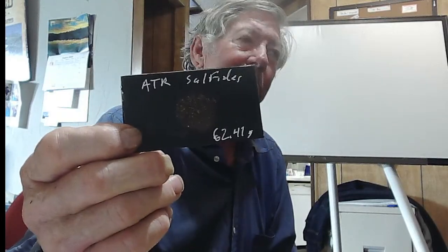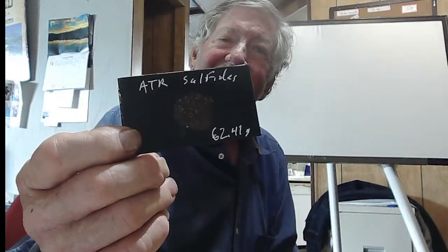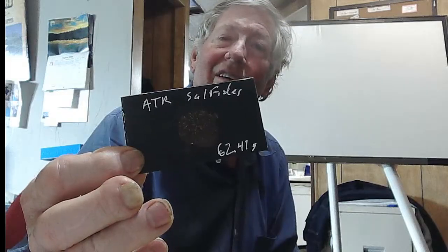I don't have a good way of taking photo micrographs right now, but I don't even need that. In some ways, I would presume this is a little better than a photo micrograph, because you can always go back to it. Once I roast this, I'll be roasting this tomorrow, then you do a similar card with the roasted concentrate and how much that weighed also. I seem to be getting, at this point, about a 25% reduction in mass, which, if I'm doing the chemistry right and the molar math, I'm actually losing a little more than I should be. I'm not sure what else is volatilizing besides just oxidizing sulfides. But anyhow, that seems to be a nice system.